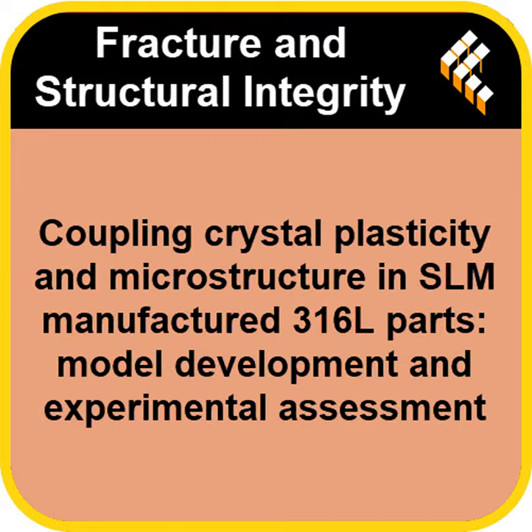That's impressive. What about the numbers for yield strength? That's the key metric, right? The 0.2% offset yield stress. The model predicted it would be 519 megapascals, the actual experimental value, 516 megapascals. Wow, a difference of just 3 MPa. That's incredible. It really confirms that getting those microscopic details, especially the twin distances, is the secret sauce.